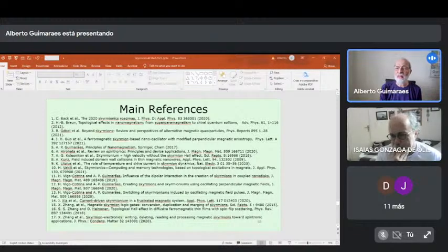This is the range, and then one looks in the simulation for the materials that provide these exchange values, and the value of the DMI interaction, which arises either in the bulk of the material when there's no center of symmetry, and in the surface, there are contributions that arise from the surface.